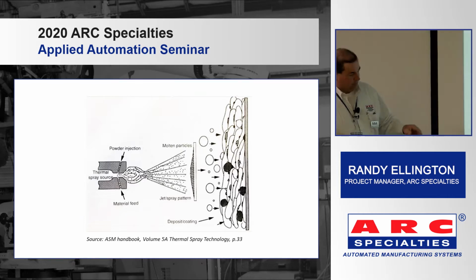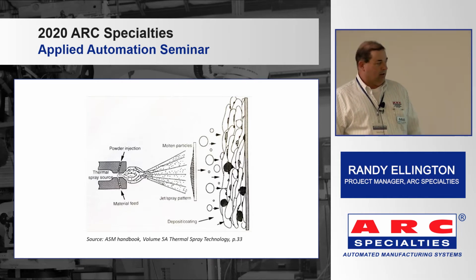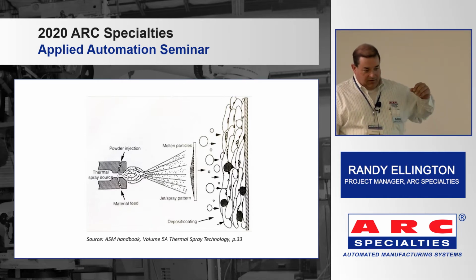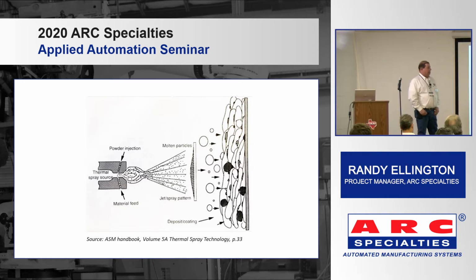Before I leave this picture, probably the most important thing along that is the dwell time that the material is in the flame. If you don't give it enough time, you don't get that plastic state, and most of the material will hit the substrate, and since it's not plastic, it's going to bounce. And a little bit later, I'll show you a picture of the guy actually spraying by hand, and he's wearing a hood, and it's because it's annoying when you're spraying this if all that bounce is coming back and it just pecks at your forehead, and it drives me crazy.